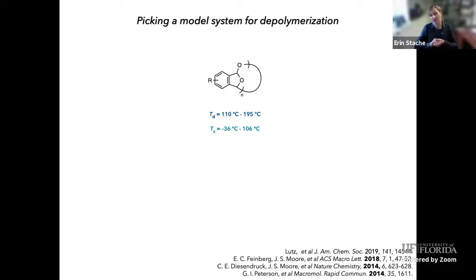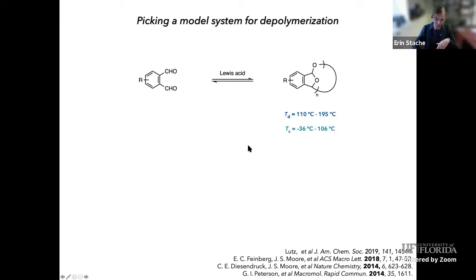And so we picked cyclic polyphthalaldehyde, which has been extensively studied by a number of different research groups. Anne McNeil, who gave a talk last week, although I don't think she talked about this, Jeff Moore, and a number of other groups. It's a self-immolative polymer, and so when you heat it up above its degradation temperature, it tends to depolymerize back into monomer. Depending on the substitution pattern, which is what we really liked, we can change the degradation temperature. And so if we put more electron withdrawing groups on here, we can raise the degradation temperature, which now gives us a gradient of temperatures to look at. And this also changes the ceiling temperature.